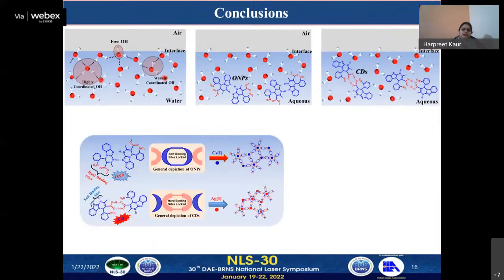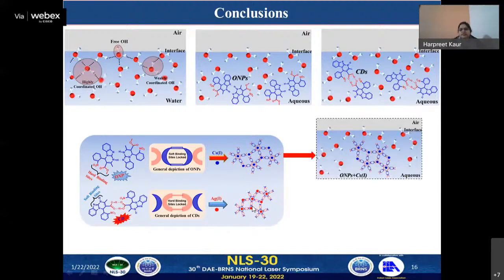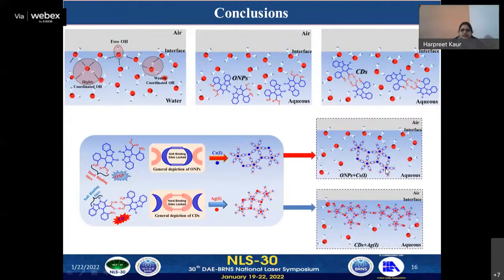And from the fluorescence study, we have found that organic nanoparticles preferably bind with the copper(II) ion, whereas carbon dots selectively bind with the silver(I) ion. And their interfacial study has shown that organic nanoparticles, while binding with copper(II) ion, prefer to stay in bulk, whereas carbon dots, preferably binding with silver ion, show surface coverage at the air-aqueous interface. So this is about the sensing activities of the nanomaterials at the air-aqueous interface.